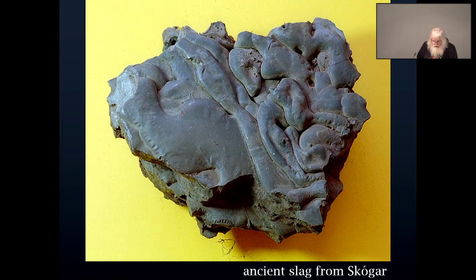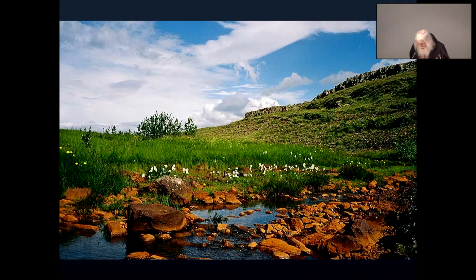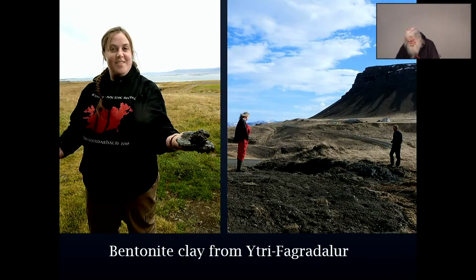Then we started looking at the raw materials that might have been available to the Viking Age Icelanders. First of all, the iron ore. Now, red earth is found in or near bogs, and it's available all over Iceland. Large quantities are available. Now, we need clay for the walls of the oven. The clay, first of all, resists heat, but more importantly, it participates in making the slag that is necessary for protecting the iron at the bottom. And here we found a big problem. The clay that's readily available here in Iceland is bentonite made from volcanic ash. And it's not suitable. So we'll talk more about that in a minute or two.